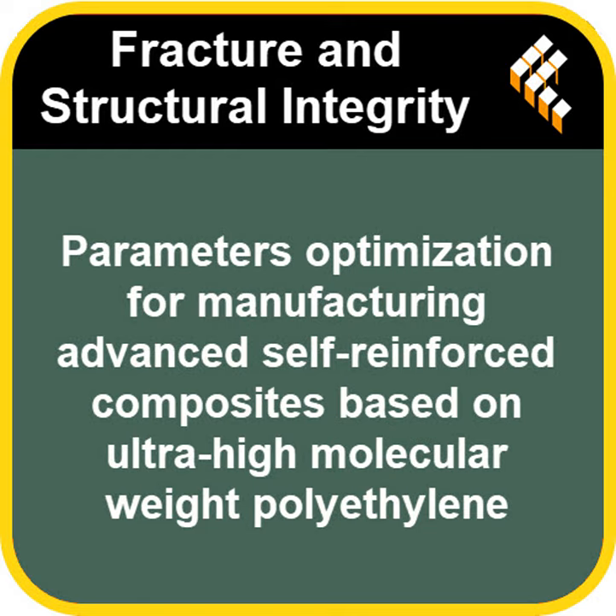It really sounds like a balancing act. Get enough melting for bonding, but not too much. That's precisely the challenge. It's a very fine line. So what did the researchers see when they looked closely at the result? They used electron microscopy, right? SEM. They did, and they saw something really interesting about the fiber shape within the composite. The individual fibers weren't round anymore. They deformed into a sort of hexagonal shape.